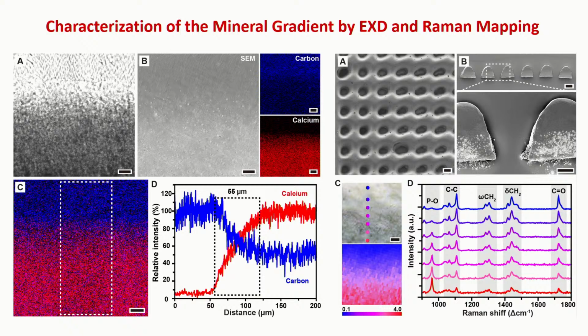And here is the SEM image of the top and the cross section of this film. In this case, we already switched to the femtosecond laser in the IEN. That can provide much better resolution when we do this kind of laser micromachining. And then we can also characterize this cross section using Raman mapping. You can map, for example, two different functional groups. One is this C=O group, that's for the PCL polymer. And then you have the phosphate group, that's for hydroxyapatite.